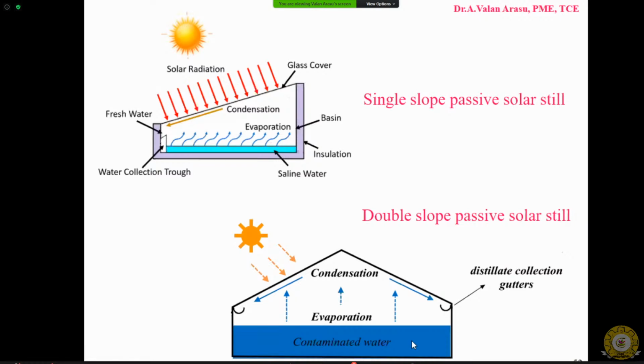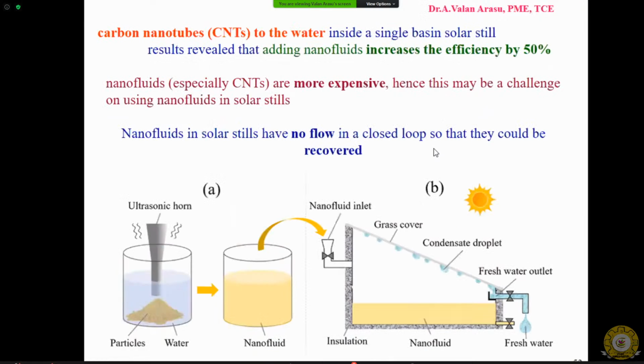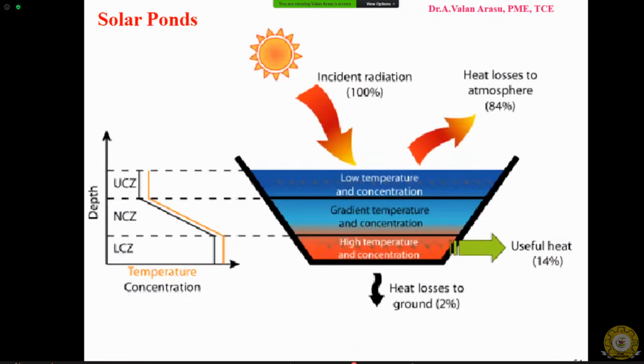Okay. So by adding this nanoparticle to this brackish or salty water, it's found that the rate of evaporation is increased, and hence the efficiency of the solar still is increased. When carbon nanotube is used, it was found that the efficiency was increased by 50%. And of course, here there is no loss of nanoparticles, so we can recover the nanoparticle and use it again and again for the preparation of this nanofluid.